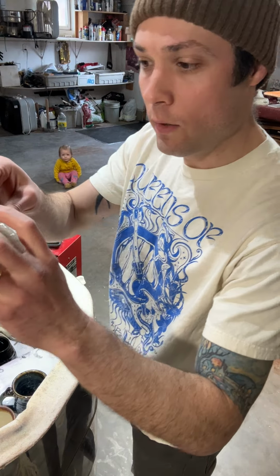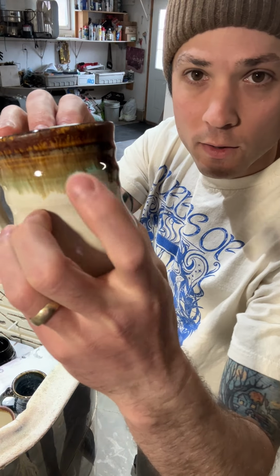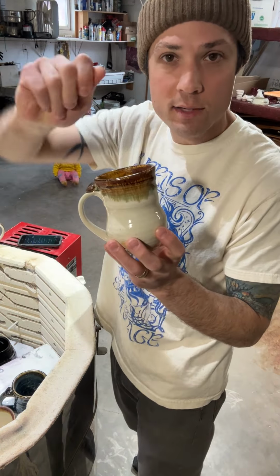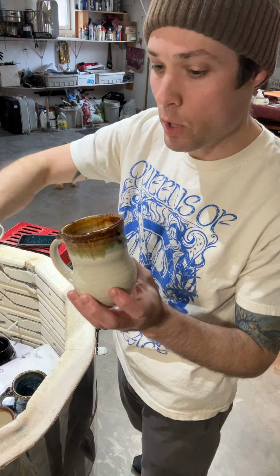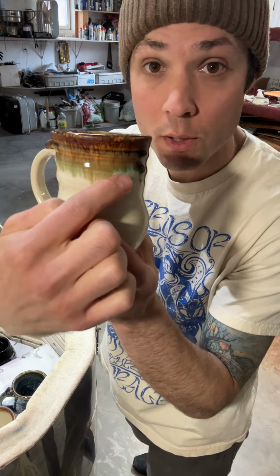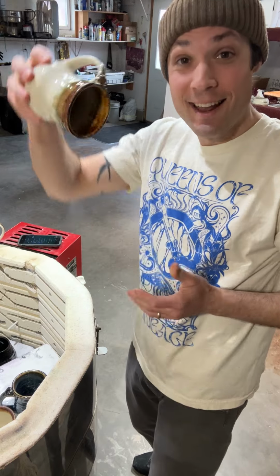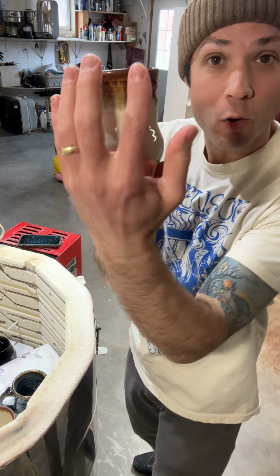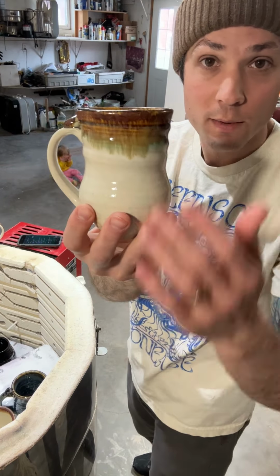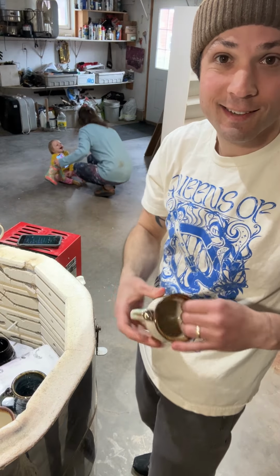When you see green, that's copper. So iron, copper. What I did was I brushed iron oxide mixed with water on the rim, and I brushed copper carbonate mixed with water just below the iron. Then I dip in the ash glaze, and it all runs vertically down this way, mixing with the metal oxides.